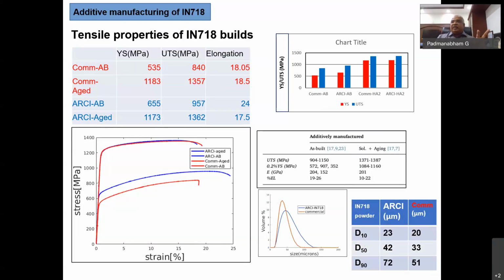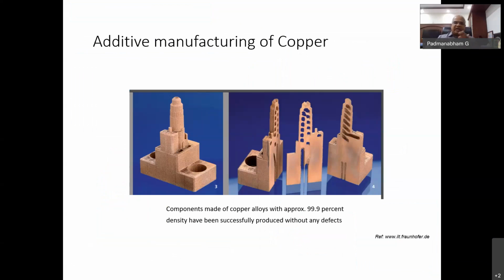So what I mean to say is we are able to make indigenous powders, and in this case the material is reasonably AM friendly, and we also saw that the wrought material as well as the AM built material are responding to the heat treatment in a similar fashion, and the volume fraction and distribution of several phases is also the same in both the cases, because of which we'll be able to predict the product properties better and implement this AM material into production. Now I go to a little challenging material like copper.